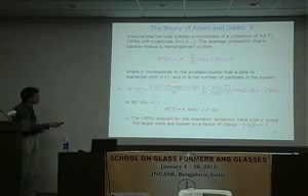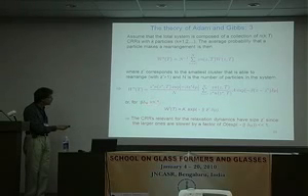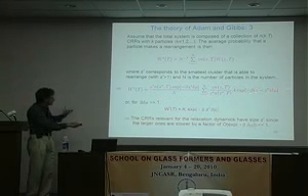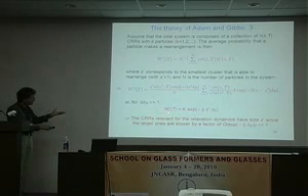And so you plug in the expression that we had here. In this equation, you fiddle around a little bit and you get this expression. So you have a prefactor, which depends on this Z star, and then you have times something. But if beta delta mu is much larger than 1, that is to say, if the temperature is very small, then all these factors become very, very small. That is to say, you can stick with the first term, and the first term is just 1. So you can throw away this sum or replace it by 1, and you end up with this. All the stuff that you don't like, you put in a constant A prime. So the end result is that the probability that the particle flips is proportional to this quantity here, where Z star is the minimum number of particles that can flip.